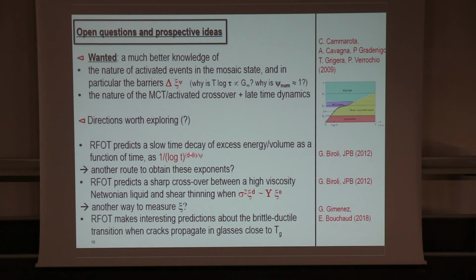For example, RFOT predicts that as you quench the system, there should be a slow decay of the excess energy or the excess volume as a function of time, that is, as 1 over log of some power, which includes theta and psi. So maybe that's another route to obtain a relation between these exponents, both experimentally and numerically.